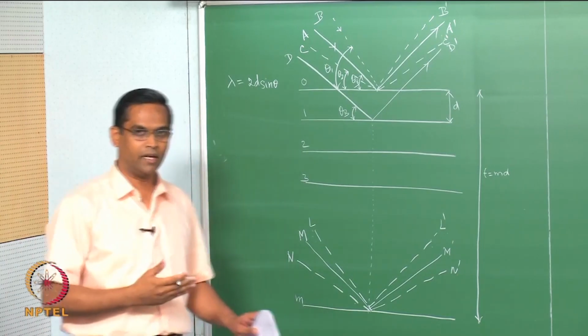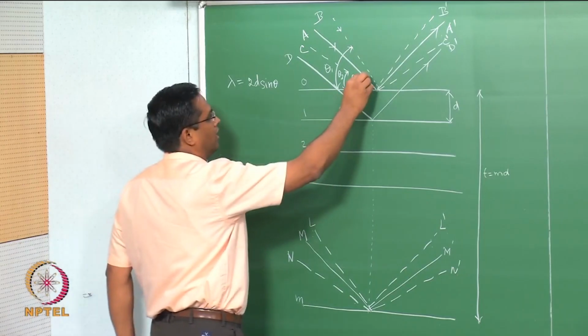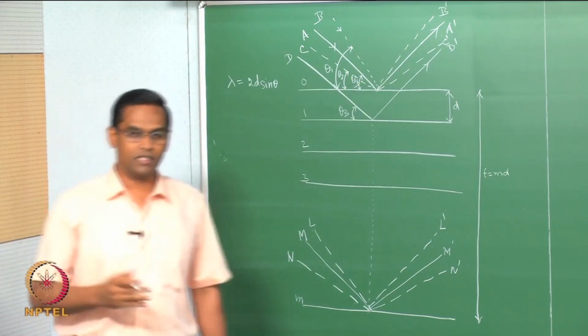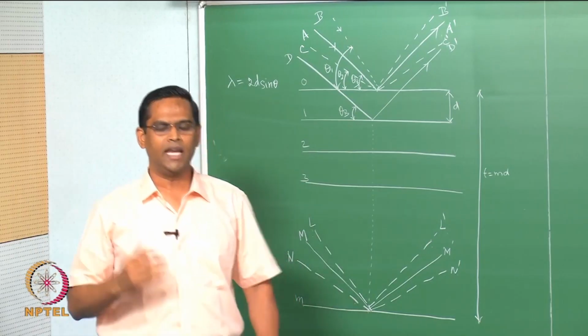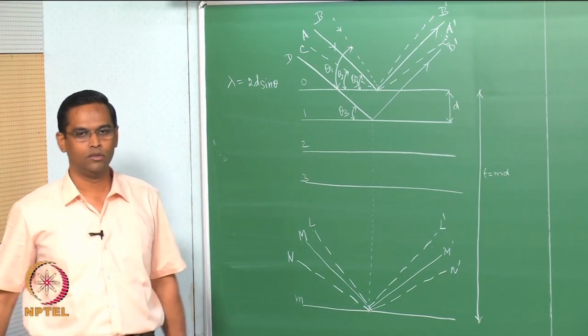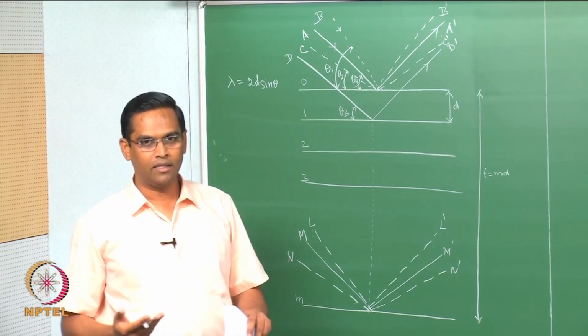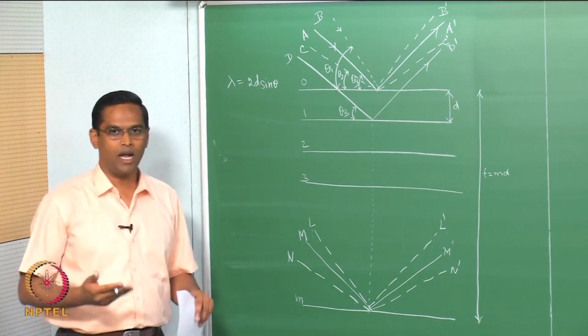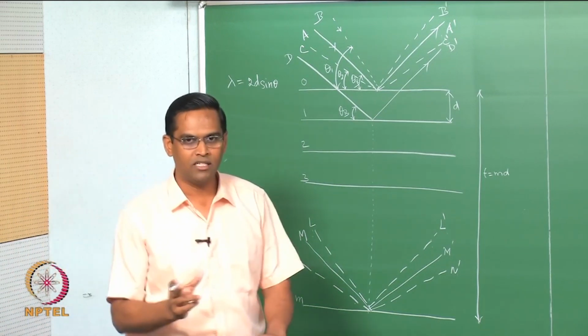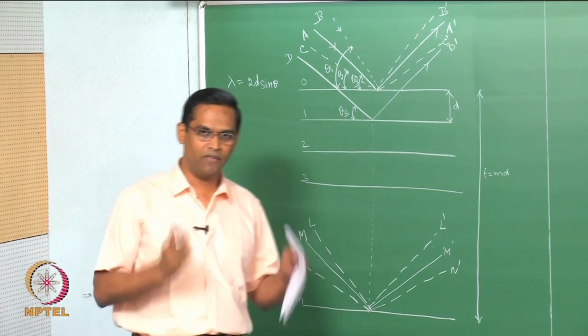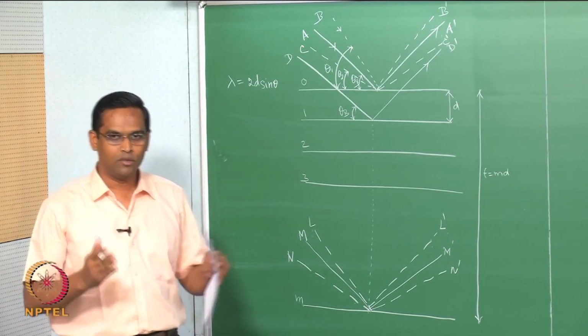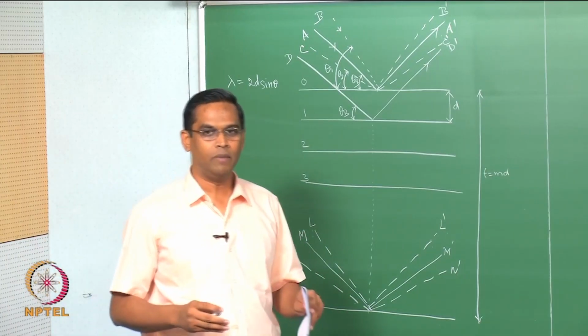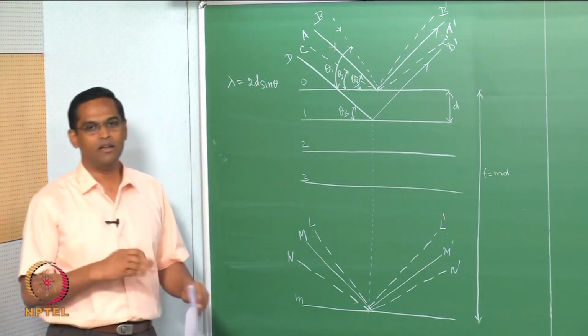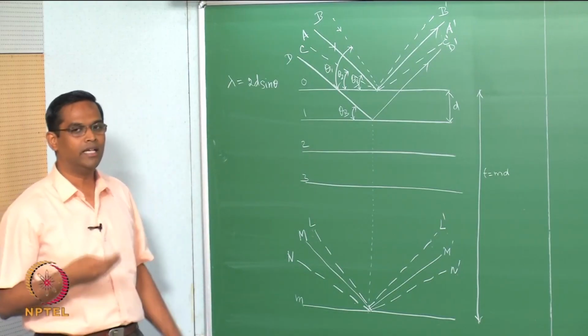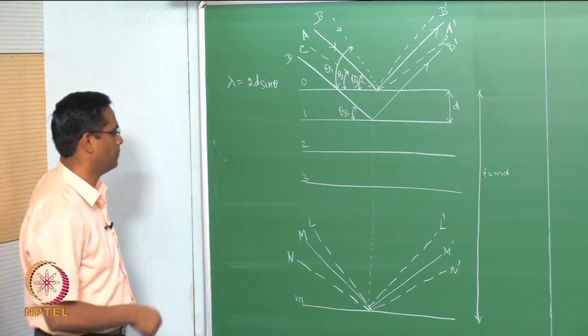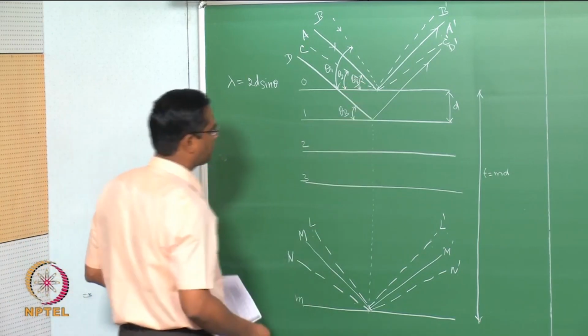So, what are we trying to say here? Since you have crystal planes which diffract slightly away from theta b, there exist two limiting angles, because we are talking about 2 theta here, since that is what we measure: 2 theta 1 and 2 theta 2. So, we are talking about a range of angles. Within this range only the intensity will vary, and these are the 2 limiting thetas where the diffraction intensity will become 0. So, that is the idea of doing all this.